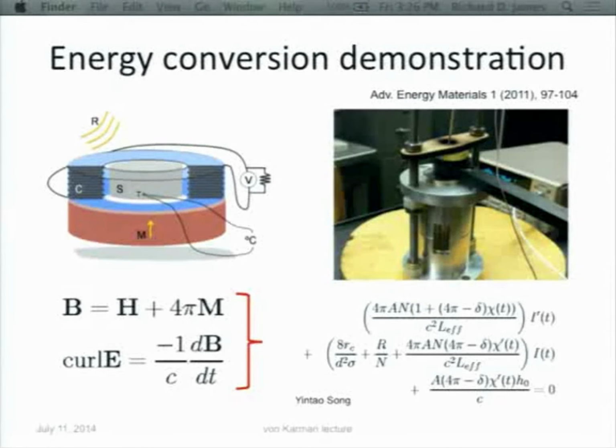But here's a more interesting demonstration that we did. We took a piece of that material, we put it on top of a permanent magnet, and we put a coil around it. And then you have to think in terms of Maxwell's equations, and you have this dipolar relation, B equals H plus 4 pi m, and you have the Maxwell equation curl E equals minus 1 over c dB dt. When you heat it, you go through the phase transformation. That gives you a big dm dt, which is, of course, partitioned between dB dt and dH dt. And how much goes to dH dt and how much goes to dB dt, that's micromagnetics. And we arranged by the shape and so forth that we get a big dB dt, and that gives us a curl E. That means there was a current in the coil.